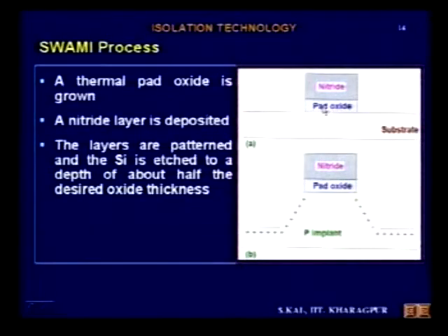So now with silicon pad oxide and nitride, if I want to go for lithography, then what will happen? When you are going to etch the silicon nitride here, photoresist will be there, covered on top of the nitride. And when you are going to etch silicon nitride, that photoresist will react with the silicon nitride etching solution. But photoresist will not react in buffered hydrofluoric acid etching, which is the etching solution of silicon dioxide.